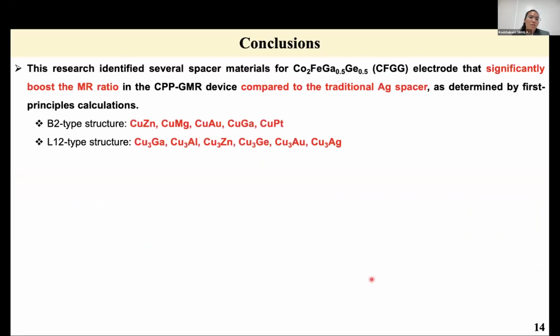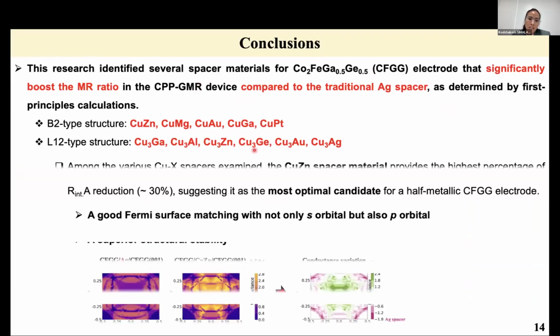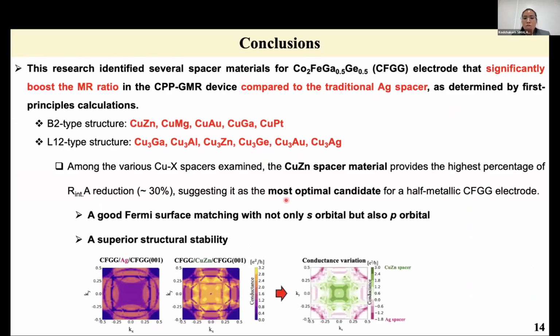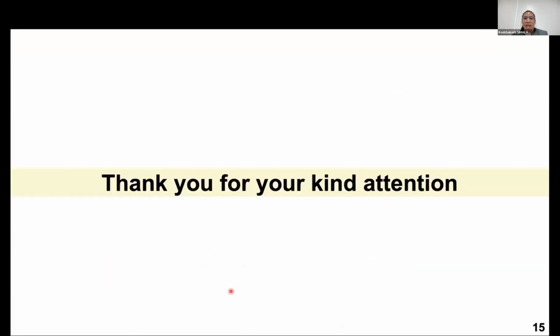So, in conclusion, in this result we can identify several spacer materials for the CFGG electrode that significantly boost the MR ratio in CPP-GMR devices compared to the traditional Ag spacer, as determined by first-principles calculation as shown here. Copper zinc spacer material stands out as the most optimal candidate for the half-metallic CFG electrodes because of good Fermi surface matching with not only the s orbital around the gamma point, but also the p orbital along the diagonal of the Brillouin zone. It also has superior structural stability compared to the Ag spacer. Thank you for your kind attention.